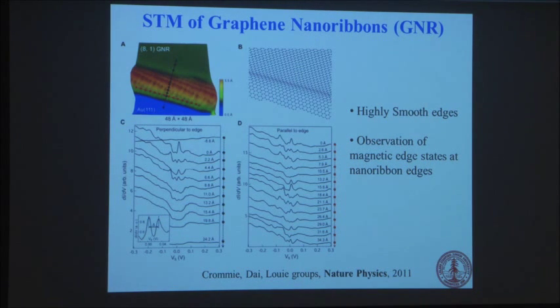And we collaborated with a physics group at Berkeley, Mike Crommie's group. And they did STM imaging of these ribbons. And this is the edge of the ribbon, and you see it's quite smooth. And as they scan from the edge to the middle, you can see that this peak here is decreasing, is disappearing as you go from here to the middle. So they interpret that as these edge states that people have predicted. So that was a pretty exciting time. So maybe these ribbons can be used to study phenomena like that. But we're still trying to improve this kind of making process. Can we really make something that's atomically well-defined and controlled?